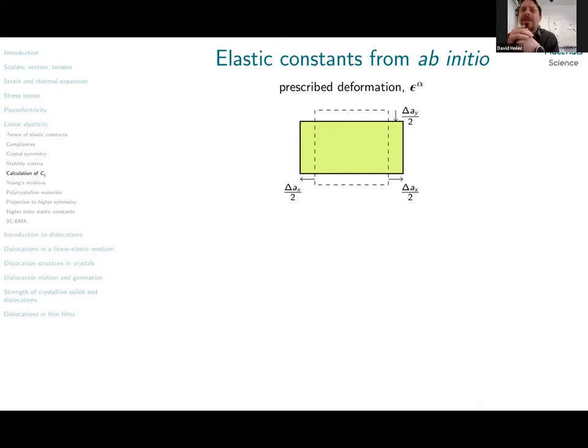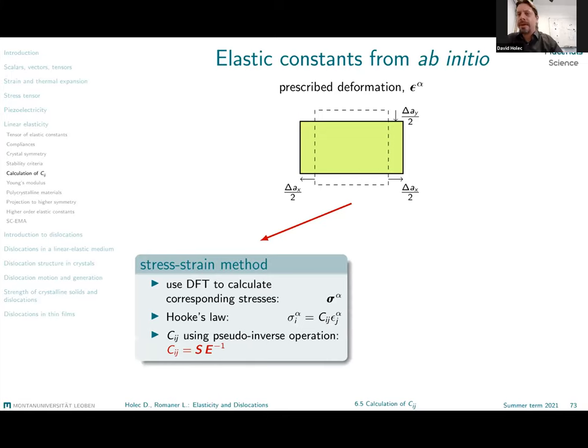Either you monitor the resulting stresses or you monitor the resulting increase of the total energy. Both of these things can be done once again on the quantum mechanical level using ab initio calculations or at the atomistic simulations level using, for example, molecular dynamics. So if you have access to the stresses, then you do something similar to what you would do in experiment. Similar, because in experiment, you are likely to apply force and measure displacement. In simulations, it is easier to prescribe displacement, to prescribe deformation, means prescribe the strain, and calculate the resulting